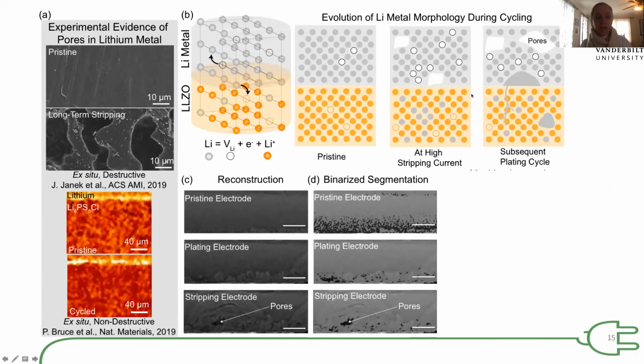These images here are from some recent papers which show the state of the art for looking at lithium pores or voids, where you can strip for long periods of time and extract the lithium metal and see how the morphology changes. Unsurprisingly, under extreme conditions, we can get a pretty ragged morphology. And then Peter Bruce's group used X-ray tomography to resolve pore formation at the lithium metal interface.